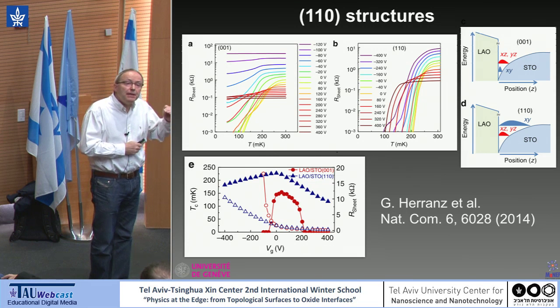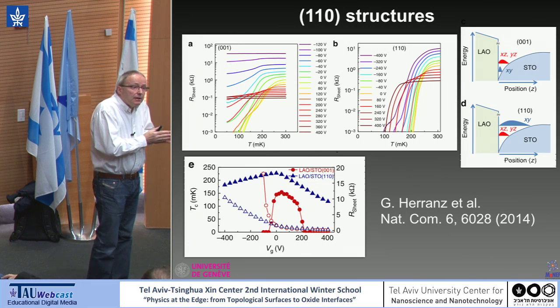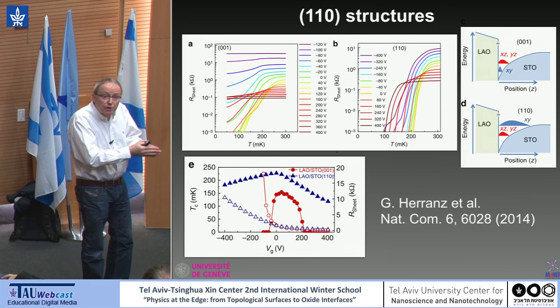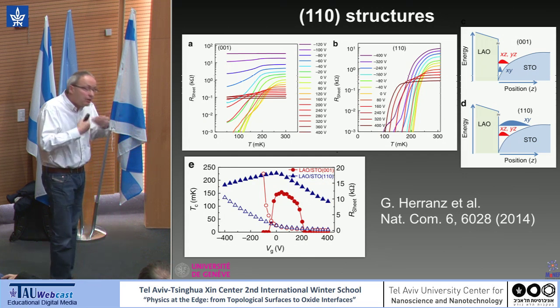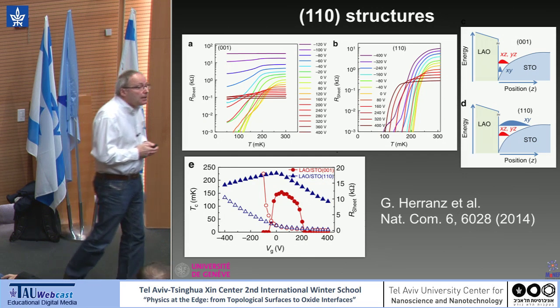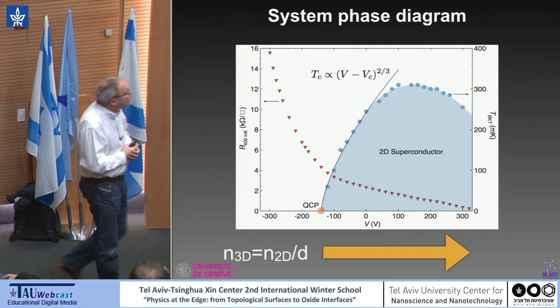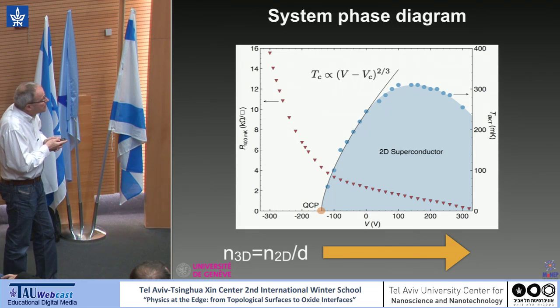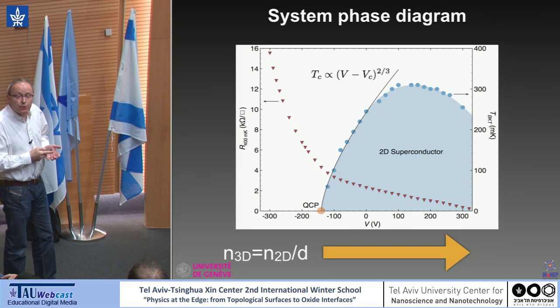So it could well be that at the interface, in the (110) direction, we observe superconductivity at higher doping because we have to fill these heavy bands. Okay, now another surprise is when we try to map this dome to the 3D dome. So what should we do?